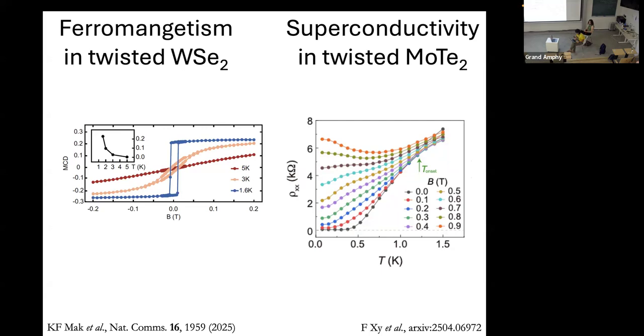So what did they do wrong? I mean, it was not that every group was not seeing it, but there are many papers where ferromagnetism and superconductivity are seen in the same samples, and these samples were also cross-checked by other groups, and everybody found the same results. But then one way of fabricating it was not producing the same signatures from a different lab. So the idea was that superconductivity and ferromagnetism were coming from two different parts of the sample. It's not a pristine sample which was both ferromagnetic and superconducting. You showed that in LAOSTO, no? That there are some regions of ferromagnetic, some regions of superconducting, right? You showed that, the scanning SQUID showing something like that. There was something, but not magnetic and superconducting at the same time.